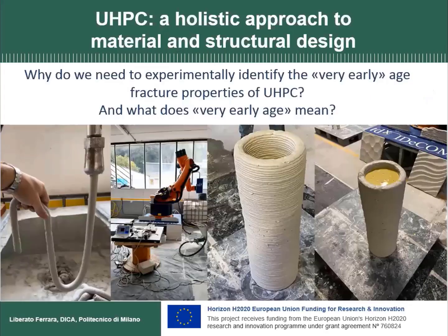Then we wanted to see: is there any correlation between the rheology and the very early age performance? The motivation for this study came from some 3D printing applications we have been working with. For example, you have to print a filament which has to resist forces during the printing, or you can print a formwork, and if you fill it with concrete, hoop tensile stresses arise. You want to know how fast you can go with this kind of application. Also in precast applications, you may need to know how fast some properties develop because you want to speed up your process, your production.